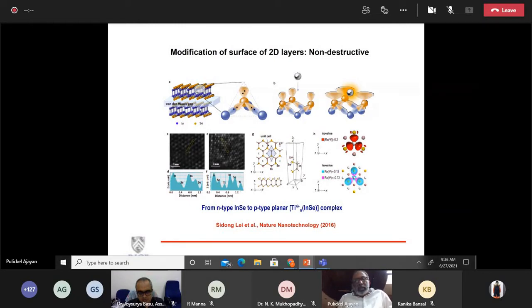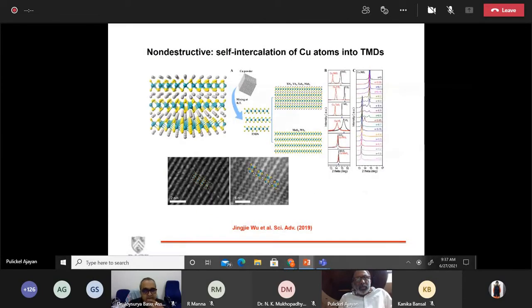There is another option where you don't really touch the topology. Let's say you take 2D materials, and without really breaking bonds, you can also change the surface chemistry by creating complexation reactions, things like acid-base or Lewis acid-base kinds of reactions that locally can change the electronic properties and create modification of surface layers and interfaces. Or you can think about intercalation. Many times the 2D materials are layered systems, so you can introduce atoms in between these layers, and that also would change the electronic properties quite significantly.